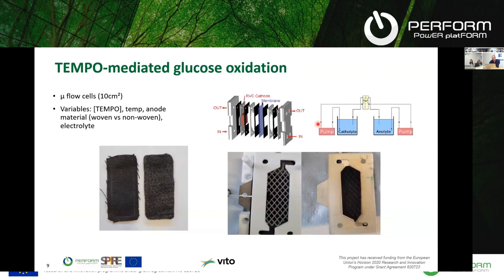So after H cells, the next step would be to use microflow cells, where you use really flow chemistry in a more realistic cell if compared to an industrial size stack, for example. This is already, especially in terms of flow dynamics, more adjacent to the final stack. In these microflow cells, we adjusted different variables: tempo concentration, the temperature. We also tested different anode materials, all carbon-based materials, since we wanted to involve low-cost materials in our process.